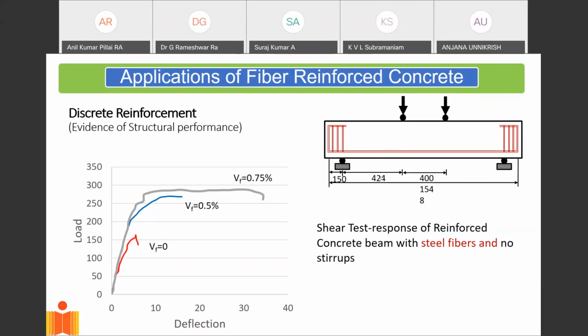So we've tested concrete beams without shear reinforcement. If I test a concrete beam without shear reinforcement, it basically fails in shear. So VF equal to 0 is where I have no fibers in the concrete. But the minute I start adding fibers to the concrete, you see that I start improving the load resistance. The peak load starts increasing, and also the ductility starts increasing.